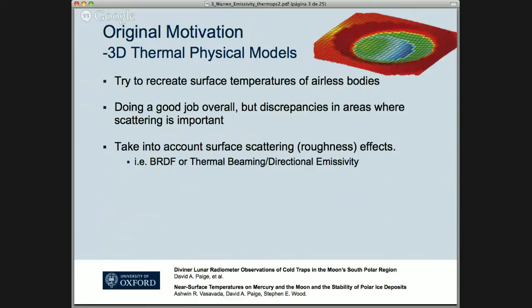If we look at a map form, one of these maps here is model data, and one of these maps is measurements we've made by Diviner. As you can see, for 90% plus of these areas, the model does a very good job. It's statistically the same, and you can't really tell these two maps apart.